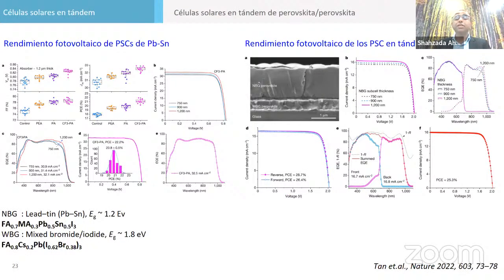In this recently published article, most people think that we have lead iodide in our material, and lead is an environmentally banned material. But the amount of lead, let me tell you, is much lower than what we use in silicon soldering or in car batteries, which is 1,000 times higher. But the community is also working on reducing the amount of lead. So you can have a mixture of lead and tin. Tin as such is not possible because tin plus 2 oxidizes very fast to tin plus 4.